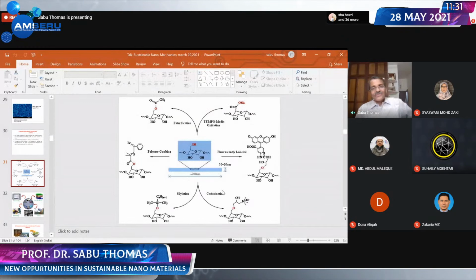Now I wanted to show you, if you're a chemist, you can do fantastic modification on the surface of nanocellulose. As I showed you earlier, you have beautiful hydroxyl groups. You can do TEMPO-mediated oxidation process. OH could be transformed into COOH. You can do esterification process. You can do polymer grafting. You can do fluorescent labeling. You can do cationization reaction. You can do silylation reaction. You can do lots of reactions on the surface of nanocellulose. You see? So wonderful chemistries could be performed on the surface of nanocellulose.